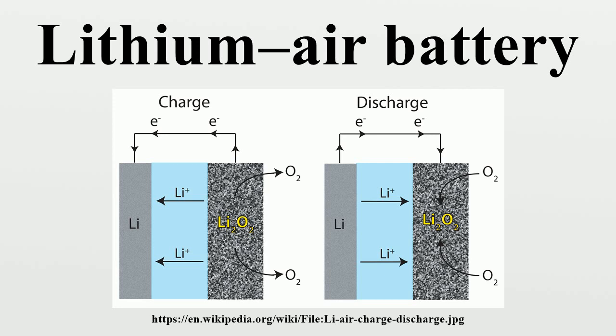respectively. Alkaline aqueous electrolyte: 2Li + 1/2 O2 + H2O -> 2LiOH. Water molecules are involved in the redox reactions at the air cathode. The theoretical maximal Li-air cell specific energy and Li-air cell energy density is 1300 Wh per kilogram and 1520 Wh per liter, respectively. The development of new cathode materials must account for the accommodation of substantial amounts of Li-O2, Li2O2 and/or LiOH without causing the cathode pores to block, and employ suitable catalysts to make the electrochemical reactions energetically practical.